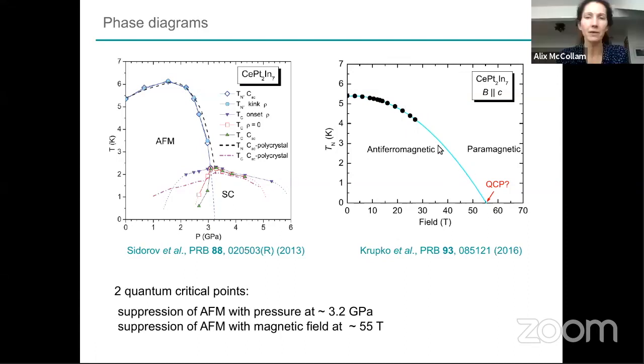We've tried a number of different techniques that should normally give us the transition point. Even transport and the torque measurements, we would normally expect to be able to see the antiferromagnetic transition rather clearly. But in this material, and in this whole family, also in cerium rhodium indium 5, cerium iridium indium 5, and cerium indium 3, it's difficult to pick up the antiferromagnetic transition in a range of measurements. Heat capacity sees it, but others not so easily. So it might be that there is something a little unconventional about the antiferromagnetic transition in this region as well.